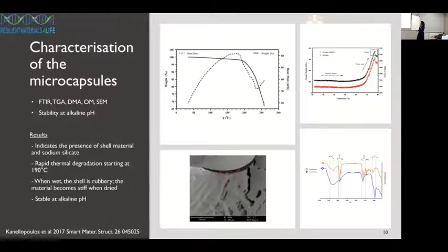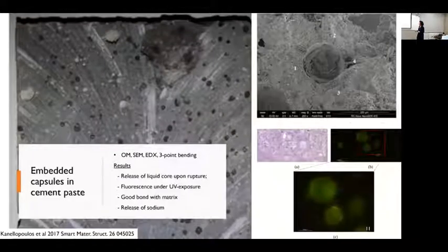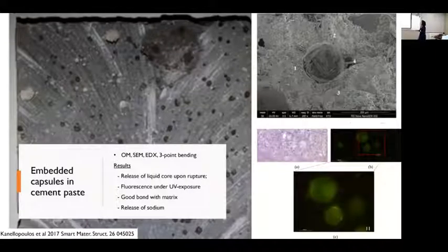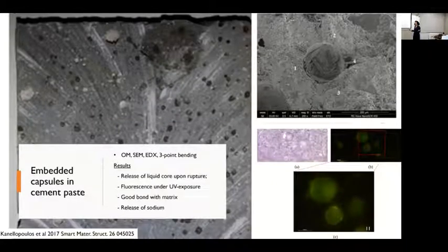Another thing that I didn't mention, but I'm mentioning now, is the stability of these microcapsules at pH, because you will, of course, want this capsule to be stable at high pH because it's the pH of the matrix. When these capsules were embedded in cement paste, it's quite interesting because you can see the release of the core immediately. I don't think that's the best image, but as soon as you break that capsule, you can see the oil coming out of the capsules. They have a very good bond with the matrix, which is quite valuable. And it's interesting that they are fluorescent under UV exposure, so you can clearly see those capsules using optical microscopy to investigate the homogeneous dispersion of these capsules in the cementitious matrix.